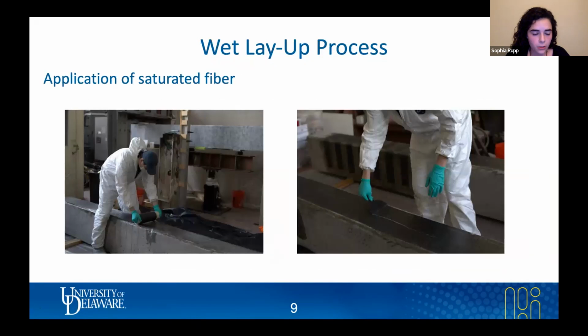Next is to then take your saturated fibers and apply it to your concrete surface, and typically take a putty knife, drag it over the saturated fibers to make sure that there's no air trapped underneath the saturated fibers or in between the concrete surface and the fibers. And then you let this sit and cure for about 72 hours, and the saturated fibers will then cure and become a composite material, leaving you with a strengthened member.